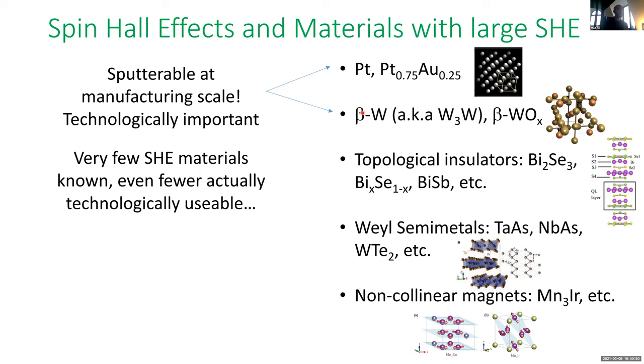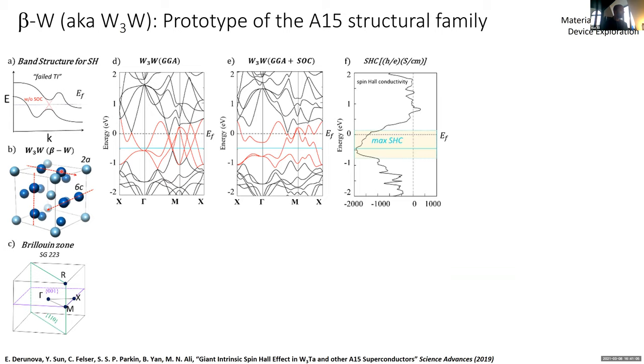When I started there, it was a puzzle. So naturally that was the assignment, to go figure that out. If you look at its electronic structure, actually, it's very, very unsurprising. Tungsten, once again, in the beta version of beta tungsten, likes to bond to itself. And so you end up with these, again, infinite chains, not zigzag this time, but linear chains in the three principal directions. And what this does is that in the electronic structure, without spin orbit coupling, just like we had hoped, you end up with lots of anticrosses. And upon applying spin orbit coupling, they gap.